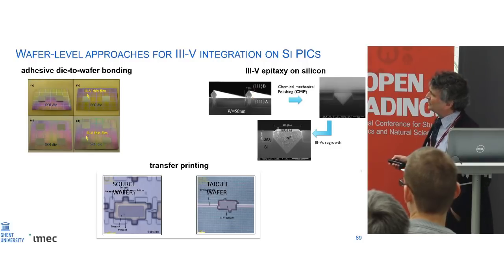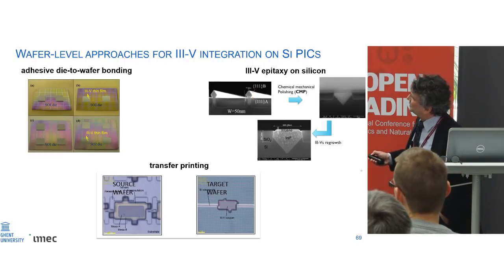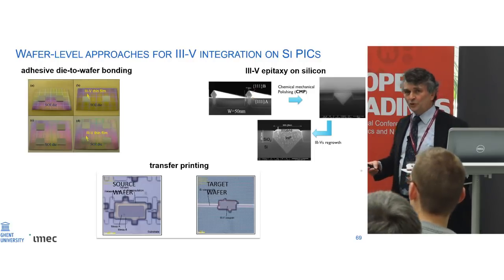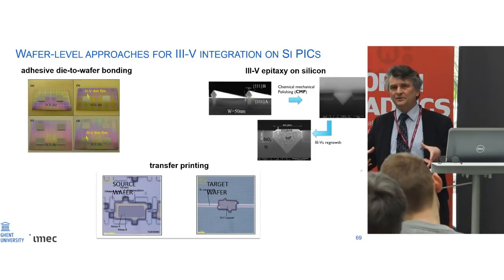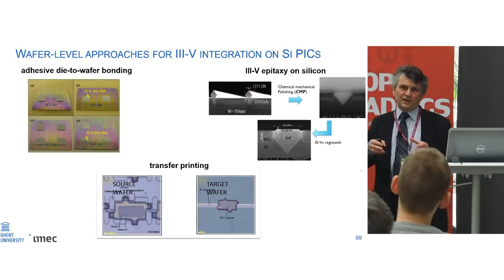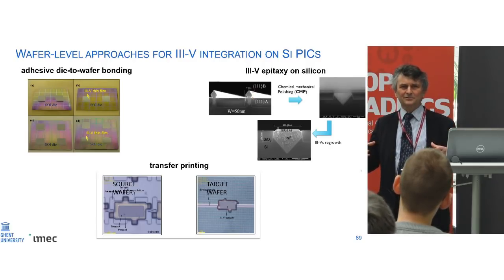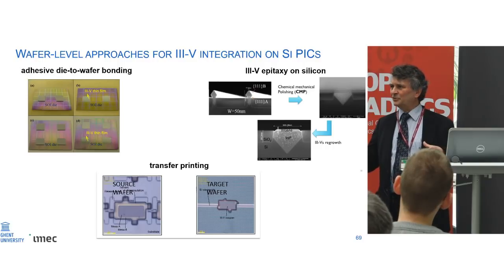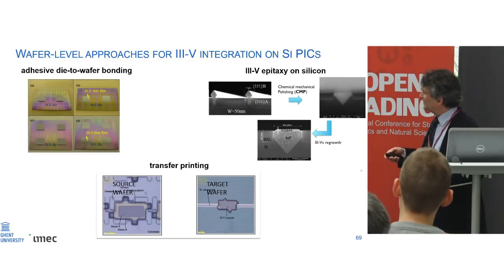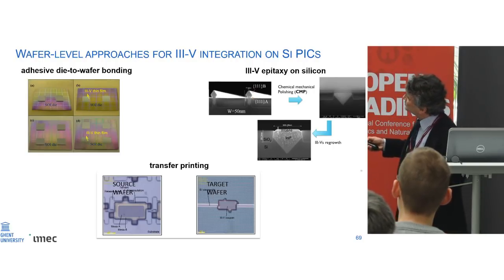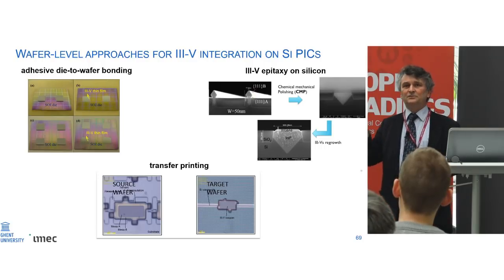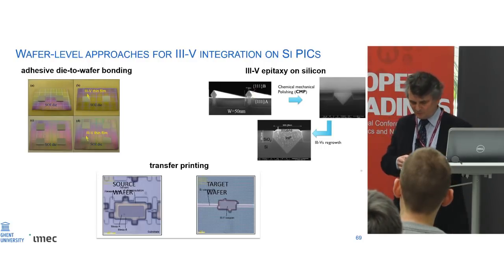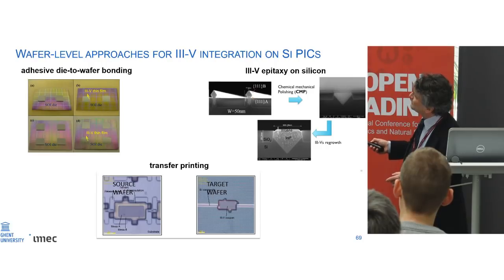and transfer printing. In die-to-wafer bonding, what you do is you work on the silicon wafer, the large wafer, but you take smaller dies or small wafers of III-V. There is not something like an 8-inch III-V semiconductor wafer, simply doesn't exist. III-V semiconductor wafers are much smaller, so you have a mismatch in wafer size. But you take smaller wafers or even individual dies, and you basically just glue them or bond them, as we say, onto the silicon wafer.